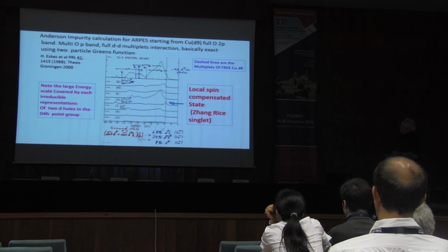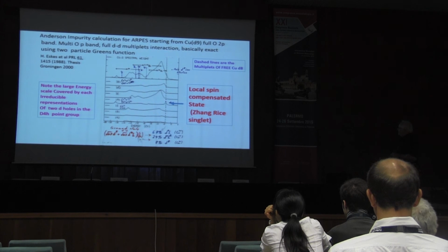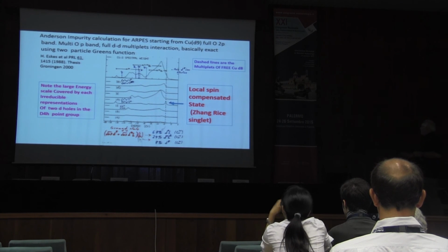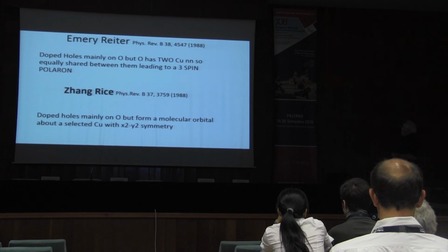And you can get all of these irreducible representations of the D4h point group for 2 d electrons. And then you find out that your multiplets spread out all over the place. Okay? But there is one lowest energy state. That lowest energy state has a spin of 0. It's a low spin state. It's a local spin compensated state. And later on, or actually at the same time, almost overlapping exactly, Zhang and Rice did it in a different way and came up with the Zhang-Rice singlet.